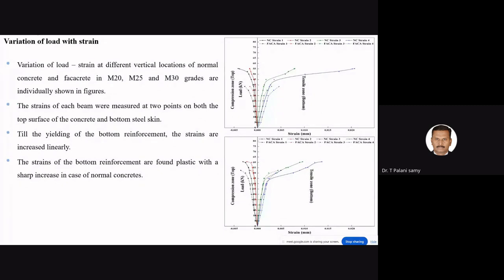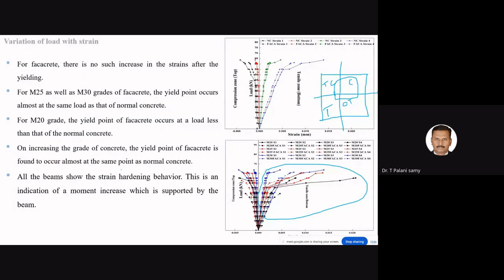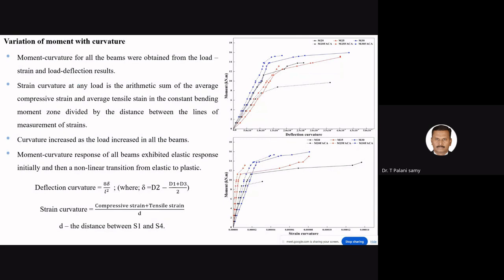So what you learn here is the variation of load with strain at the different vertical locations of normal concrete and the facacrete, M20, M25, M30, as individually shown in figures. The strains of each beam were measured at 2 points on the top surface of the concrete and at the bottom steel also. Till the yielding of the bottom reinforcement, the strains increased linearly. The strains of the bottom reinforcement were found plastic, with a sharp increase in the case of the normal concrete, all those things.